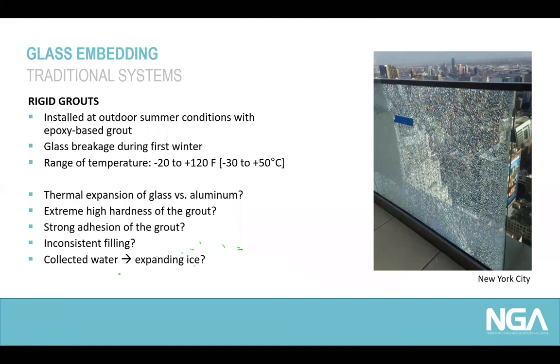Another topic is the combination of glass units in a railing system with very rigid grouts. And here on the picture, you can see glass breakage observed in a project in New York, where a glass unit in a railing system was installed with epoxy-based grout during outdoor summer conditions. Glass breakage here occurred already during the first winter. It was reported a temperature range between -20 and 120 degrees Fahrenheit between winter and summer.